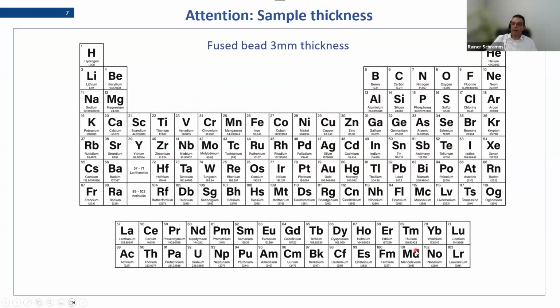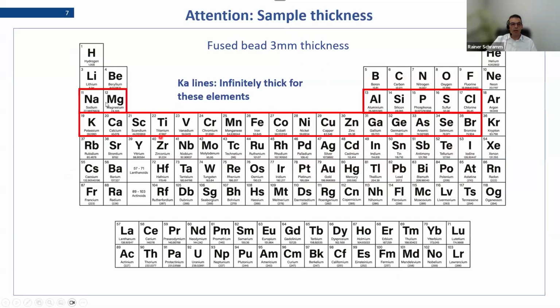Let's talk about the thickness again. Normally, I would guess that a typical fuse bead is something around 3 millimeter thick. And if we then measure our elements, for example, with K-alpha lines, then it's these red marked elements where the bead will be infinitely thick. So here you don't need to take into account the bead thickness.